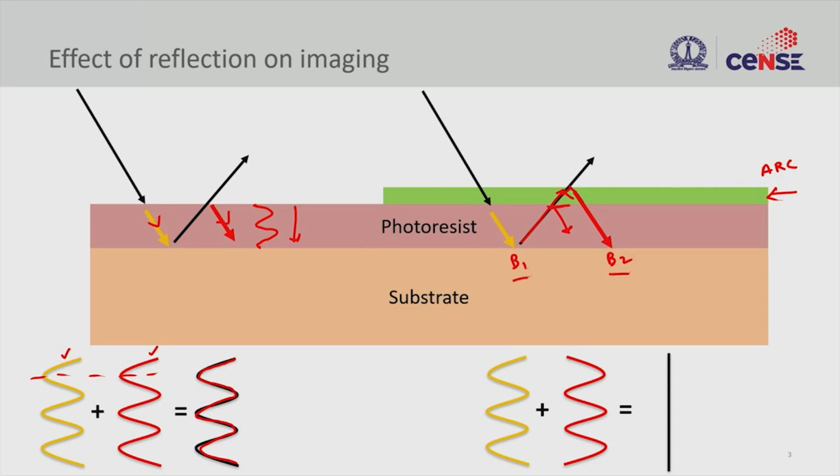So, now beam 1 has the same phase, but beam 2 has acquired opposite phase. If you look at the phase here, they are completely opposite phase, right, and this is achieved by adding this layer. So, this layer acts as a phase shifter now, okay. So, this will give a pi phase shift to the reflected beam, and when these two beams B1 and B2 interfere, it will create a destructive interference, right.